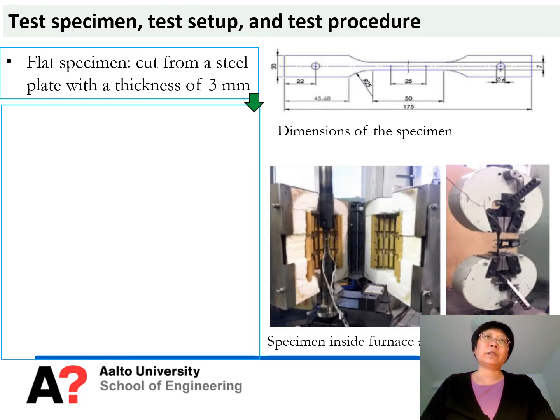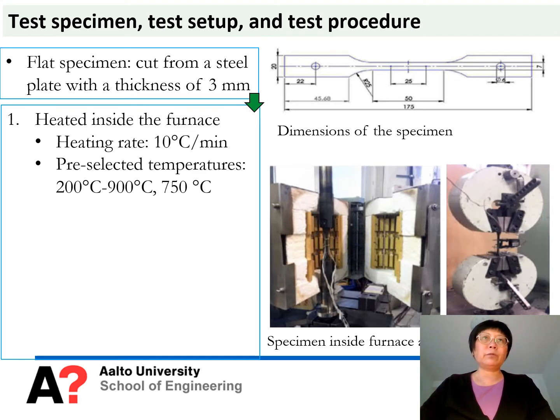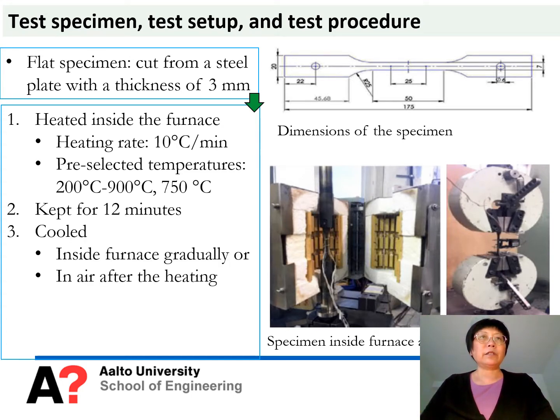The specimen was flat and was cut from a steel plate with a thickness of 3 mm. The specimen was first heated inside the furnace with a heating rate of 10 degrees per minute to some pre-selected temperatures, and after that the specimen was kept inside the furnace at the selected temperature for 12 minutes. Then the specimen was cooled inside the furnace gradually to room temperature, or immediately removed from the furnace to air after the heating.